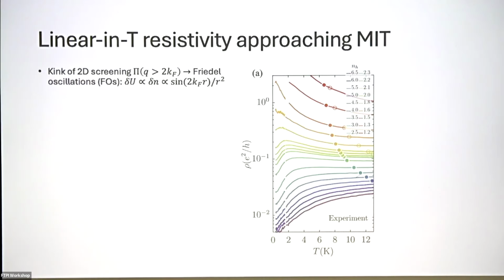At that moment, the empty states and the occupied states have the same numbers, no matter how much you shift the scattering momentum. However, the energy difference between those states keeps increasing. So it's like you are looking at a band insulator and increasing the band gap. By increasing this energy difference, you are decreasing the screening.